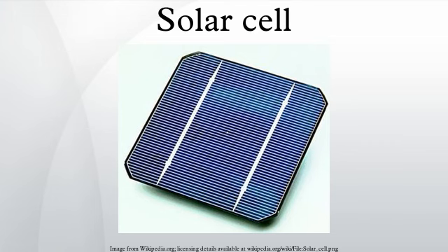Quantum dots. Quantum dot solar cells are based on the Gratzel cell, or dye-sensitized solar cell architecture, but employ low bandgap semiconductor nanoparticles, fabricated with crystallite sizes small enough to form quantum dots, such as CdS, CdSe, Sb2S3, PbS, etc., instead of organic or organometallic dyes as light absorbers. The QD's size quantization allows for the band gap to be tuned by simply changing particle size. They also have high extinction coefficients and have shown the possibility of multiple exciton generation.